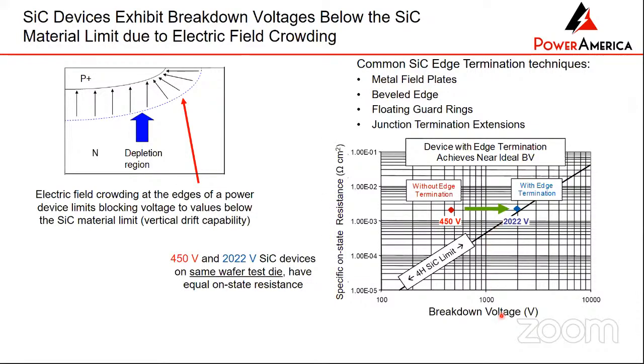You can see in this graph that shows breakdown voltage versus resistance. I made two devices that were identical. The only difference between them is that one had an edge termination and the other did not. In one case, the problem of this electric field buildup was alleviated with the edge termination. In the other case, it was left as it is. If you put no edge termination, the device will only do 450 volts. It won't get to the theoretical capability of the thick layer. If you do a good edge termination, that same device will get to 2000 volts. That's the advantage of using edge termination, and all power devices will have an edge termination because of that critical electric field problem.